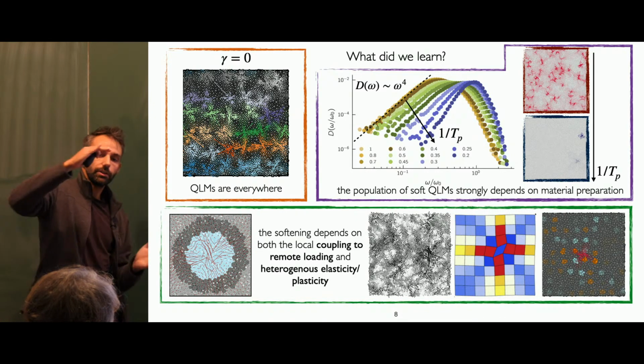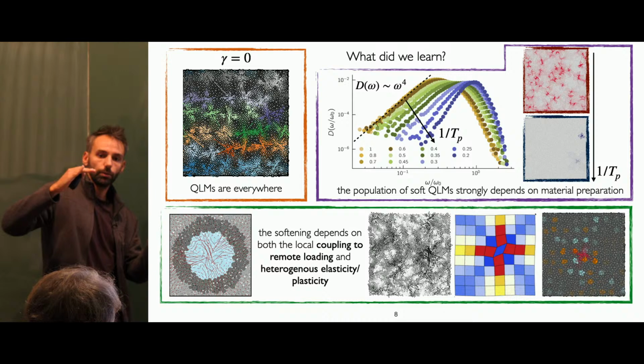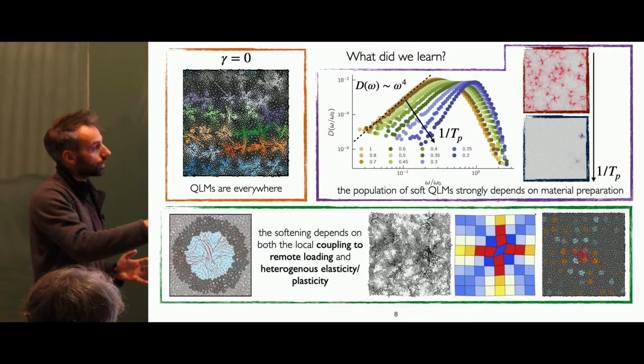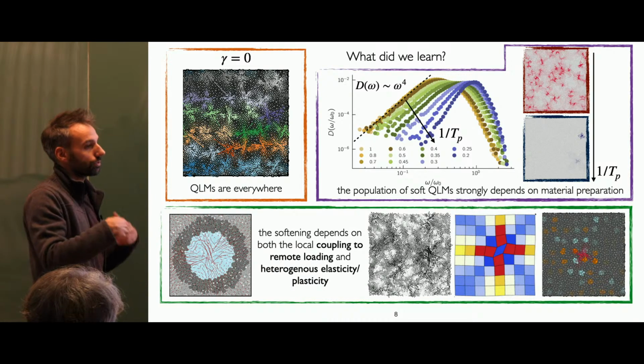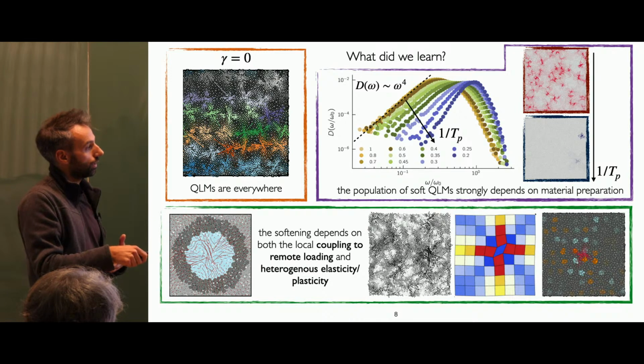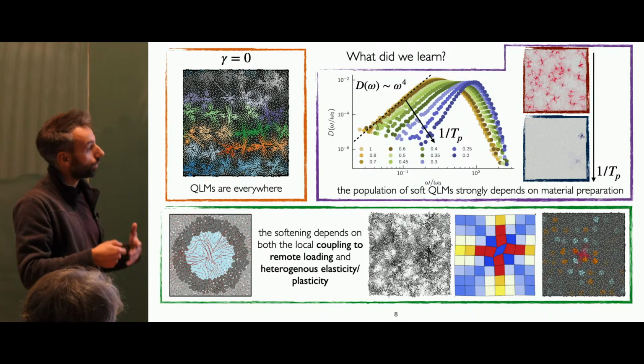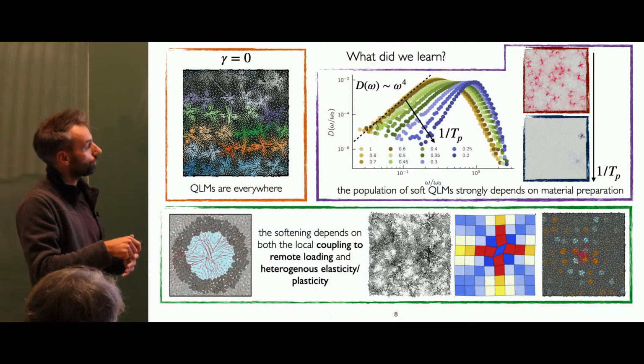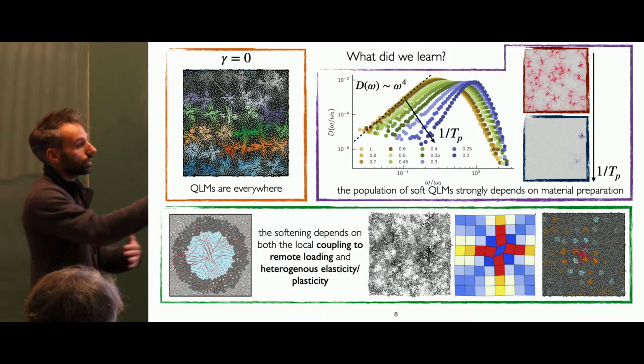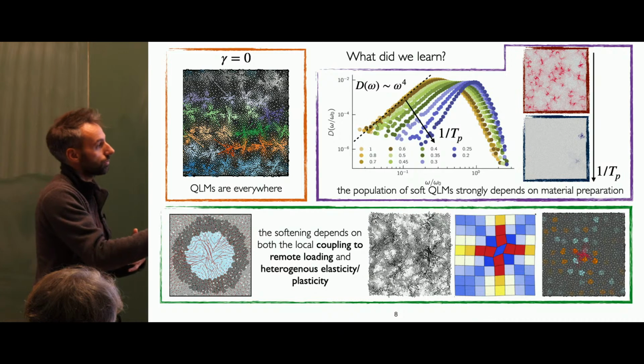The system will affinely deform, but then to restore mechanical equilibrium, it will respond to that. And we already know that even without dissipation, the displacement field actually shows long-range correlation. So already through elasticity, those soft modes and their dynamics will be influenced, at the level of just elasticity and not even dissipation.